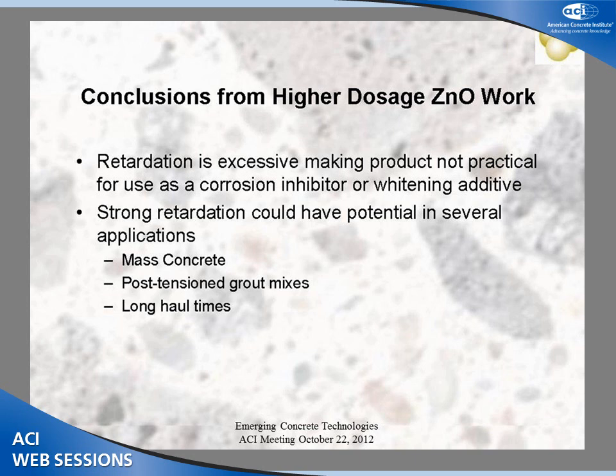Now, what are some of the positives that we can come away with using its strong retarding effects? There could be a potential use in mass concrete, post-tension grout mixtures, or concrete that has long haul times associated with it. There's two very important things that mass concrete should have. I use the term retardation, but a term that I like to use better is really hydration control. When we use the term retardation, it sounds like we're focusing a lot on just the setting time of the concrete. But one of the benefits of concrete that has extended setting characteristics is that we're controlling the hydration reaction, as it relates to strength and other properties of the concrete.